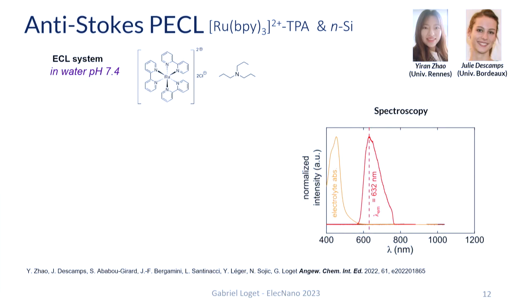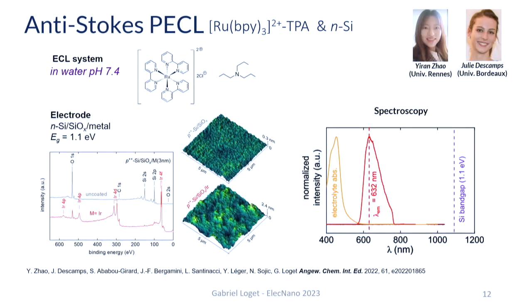In this system, we used an electrolyte which comprises exactly the same ingredients that I presented to you before in the last two slides, ruthenium trisbipyridyl and tripropylamine. Here you can see the spectral characteristics of this electrolyte: it absorbs below 600 nanometers, and our luminophore emits at 632 nanometers. Now that we have selected the electrolyte, we need to select a semiconductor to be used as a working electrode, and we wanted to use silicon.